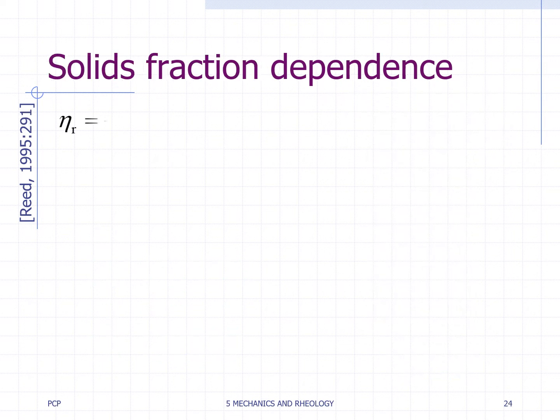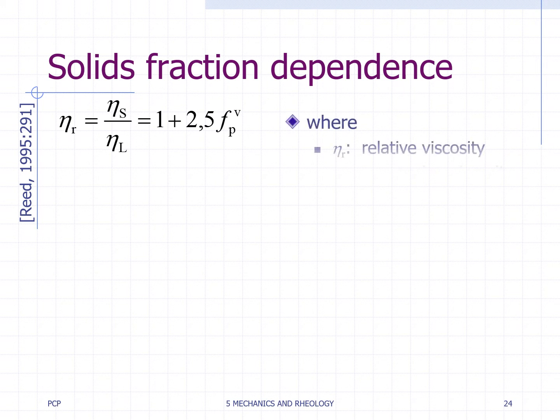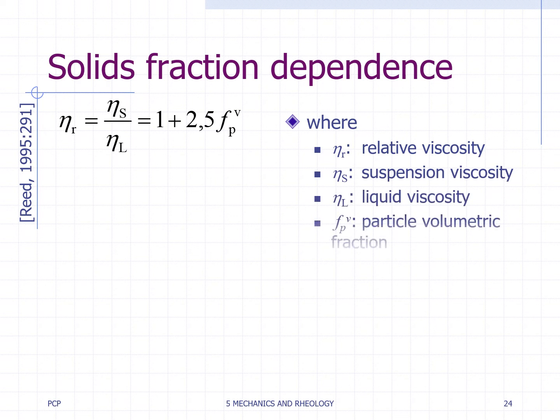The viscosity of a suspension, eta S, is greater than the viscosity of the liquid medium, eta L, in the suspension, and the ratio is referred to as the relative viscosity eta R. For a very dilute suspension of non-interacting spheres in a Newtonian liquid, the viscosity for laminar flow is described by the Einstein equation as a function of the particle volume fraction.